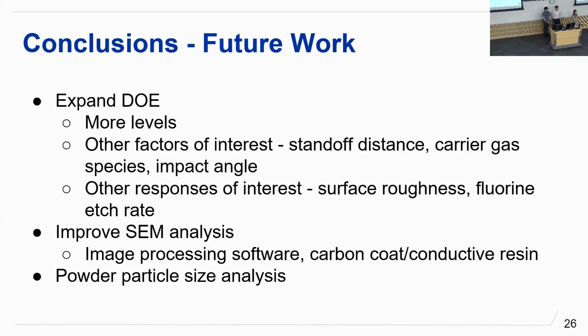We would also want to improve our SEM analysis, so likely use an image processing software to quantify our porosity rather than our eyes. And we could carbon coat our sample before embedding it in resin or use a conductive resin to improve the quality of our images. We'd also want to do powder particle size analysis to ensure that the particles we're using by our methodology are the correct size for this process.